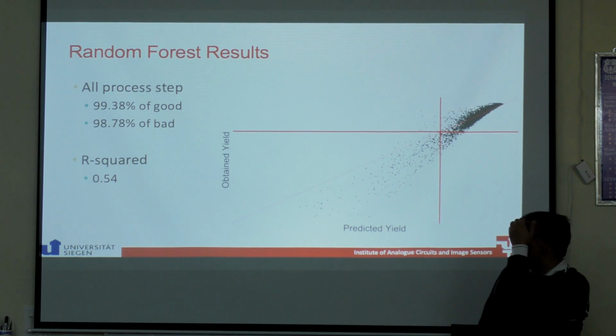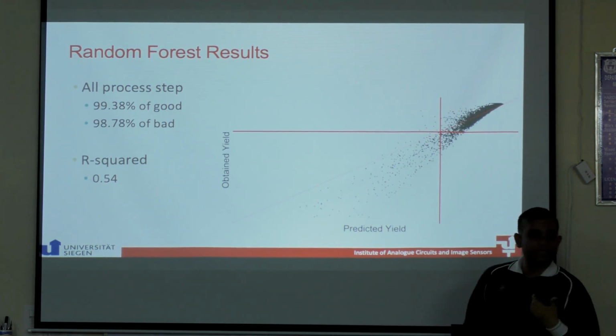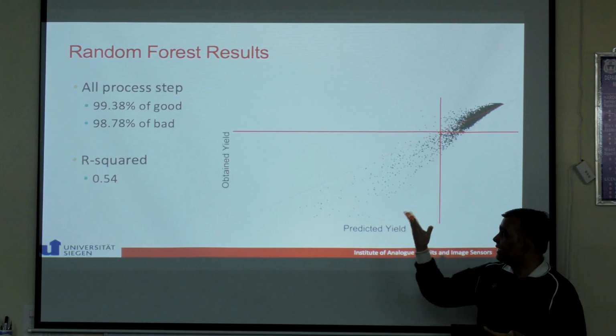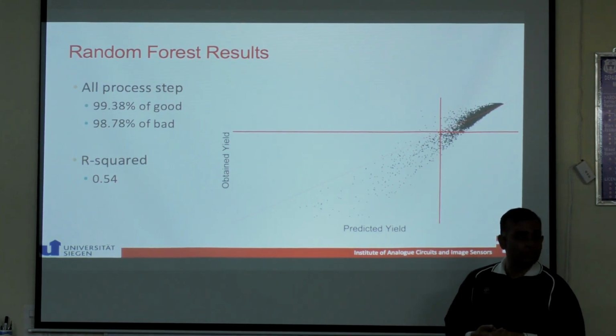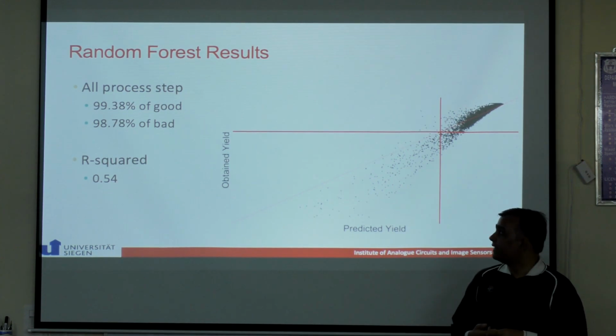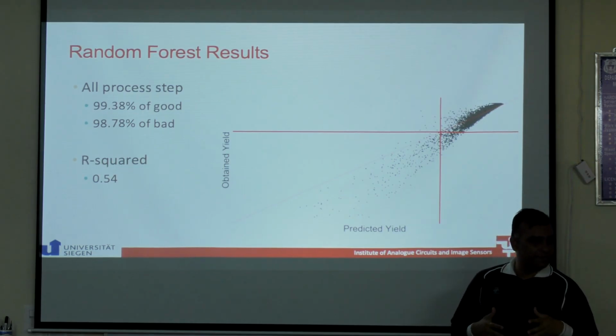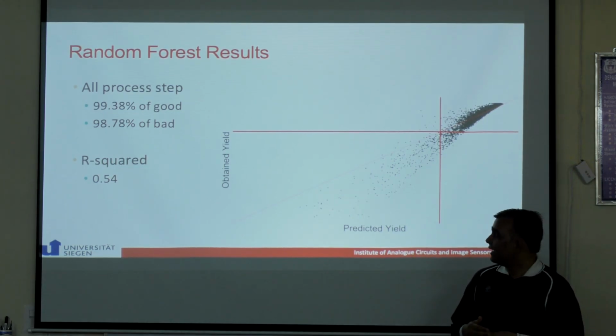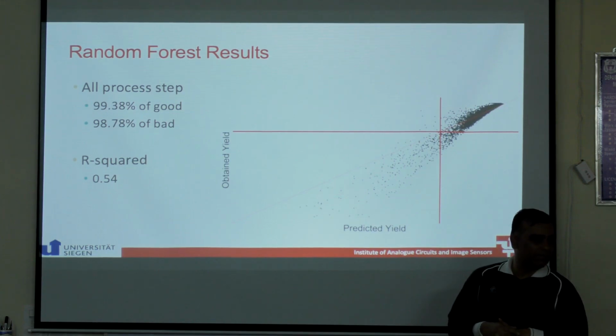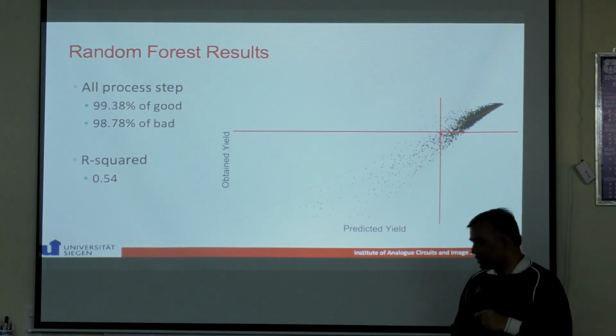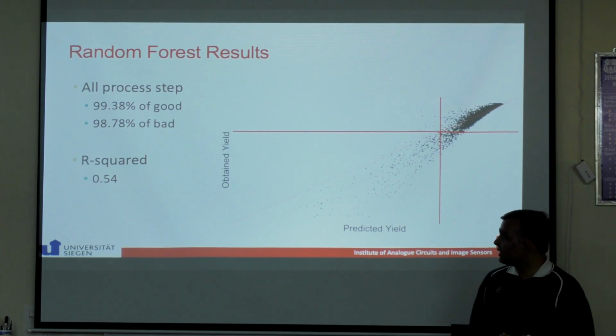When you look at all process steps, we of course significantly improve. Now we can predict 99.38% of good chips. So we only miss about 0.6% of the wafers. So few wafers we missed, and 98.78% of the bad ones. So we are doing much better approximation when it comes to that.